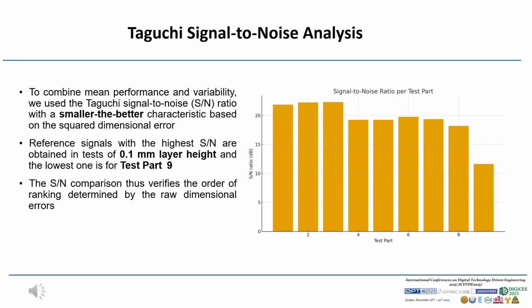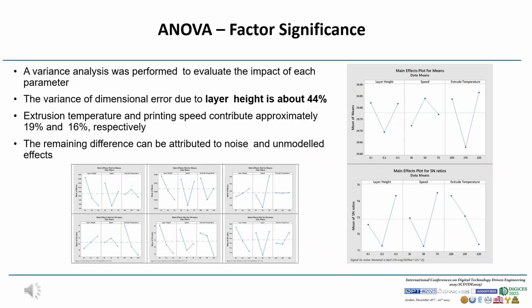desirable parameter combination. We then performed an analysis of variance to quantify how much each factor contributes to the total variation in dimensional error. Layer height is clearly the dominant parameter, accounting for roughly 44% of the variance. Extrusion temperature and printing speed contribute around 19 and 16%, while the remaining variation is attributed to noise and other effects that we did not model explicitly.